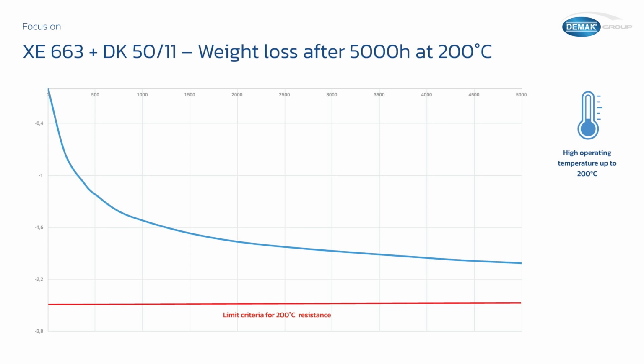Here you see the weight loss after 5,000 hours at 200 degrees. That is a reduced loss of weight, maintaining practically the same starting mechanical and electrical properties.